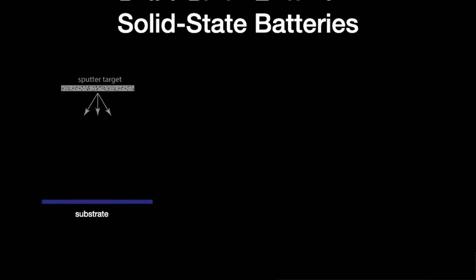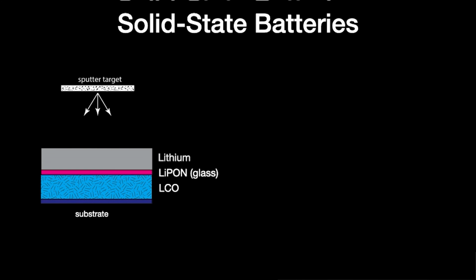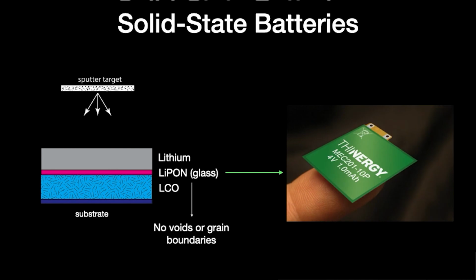Solid-state batteries have been around. Some work came out of Oak Ridge National Lab years ago, where they actually sputter deposited the battery. You sputter deposit LCO, sputter a glass, and then deposit lithium on top of it by evaporation. Remarkably, these batteries were commercialized. Several companies did it at a commercial spec of about 10,000 cycles at 100% DOD. So lithium metal cycles reversibly and quite well when it is matched up with a glass which has no voids or grain boundaries. Basically there's no place for the lithium to travel to short the battery, and these glasses are sufficiently strong to blunt lithium if it were to try to do so.